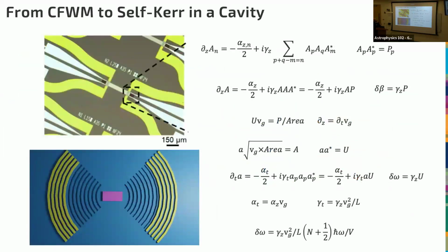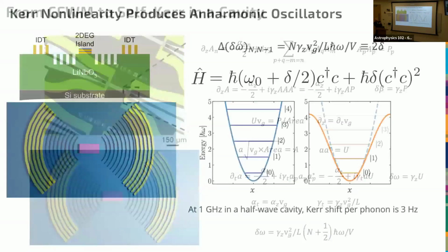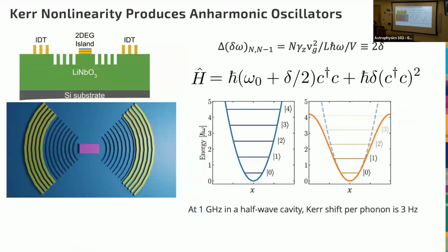If we use the measured nonlinearity in this waveguide system, essentially this collimated beam system, this is traveling, and we measure our group velocity, we can predict what the Kerr shift per phonon will be. We're doing that experiment at a gigahertz, where it would be 3 hertz. Then you'd have to make a cavity with substantially smaller linewidth than 3 hertz. That's pretty tough. But at 5 gigahertz, this gets better for multiple reasons. One is the wavelengths are just smaller, so larger field per phonon. The second is that we still have this time crunch problem here.